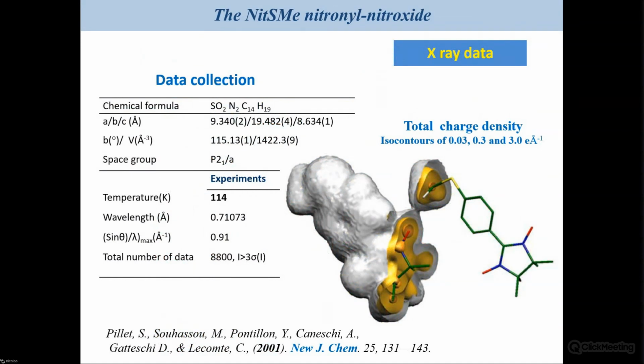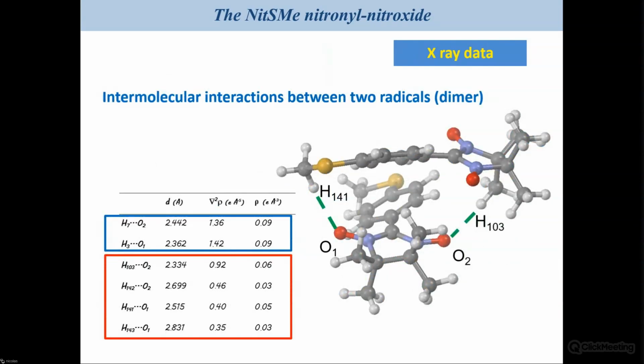Colleagues from the lab have studied that material using X-ray diffraction, and they have realized an experimental charge density model. They pointed out that it's possible, using a topological approach, to identify that specific interaction between the two radicals. And in practice, it's possible to have numbers for all the hydrogen bonds present considering a dimer. It means that you are able to observe the intramolecular hydrogen bonds that are in blue. That's a direct interaction between one part of the radical and the nitroxide function, but also contributions in red in my table coming from the inter-radical interactions. And again, you see that both O1 and O2 are involved in that interaction.